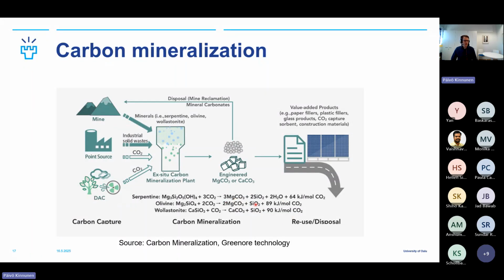Okay, so this is the carbon mineralization, and like I said, in the ex situ carbon mineralization, the biggest question is what do you do with the end product? In terms of the technological readiness level, it's still not too far. Maybe it's TRL 4 or 5, maybe could be up to 6 currently in terms of the magnesium, and the cost is somewhere around 50 euros per ton of CO2. So it's not actually that bad in terms of the costs, because you have to remember that if you do use a ton of CO2, you can get credits for that. And currently the cost of the carbon credits is about 100 euros per ton.